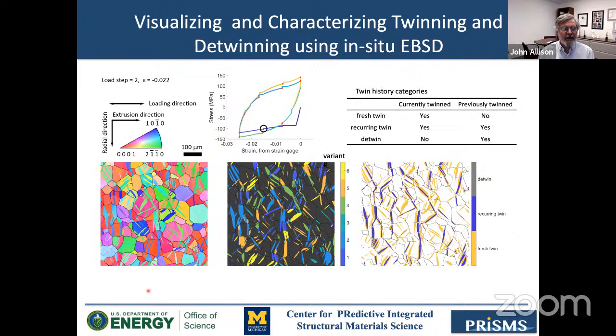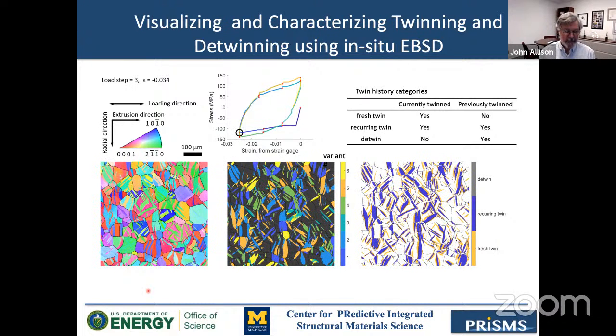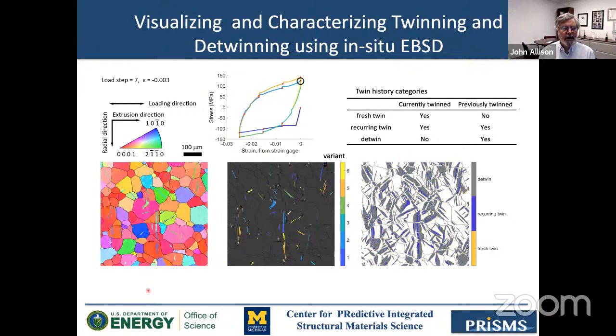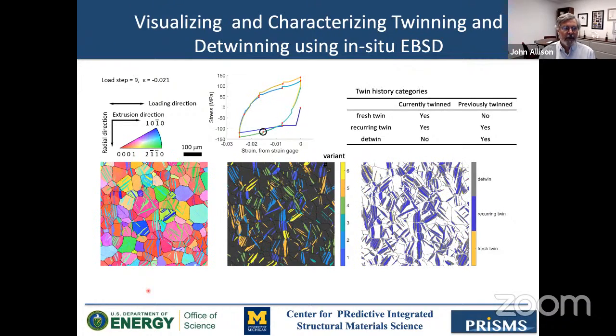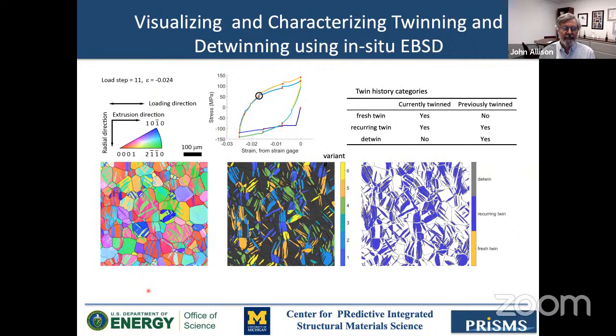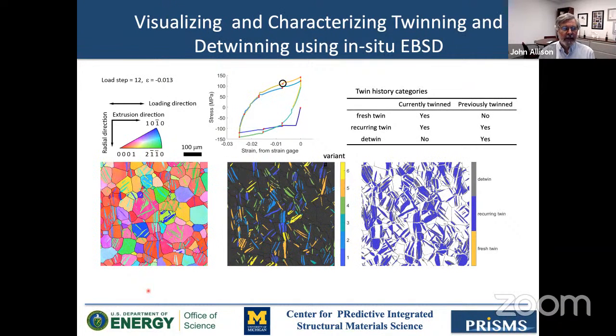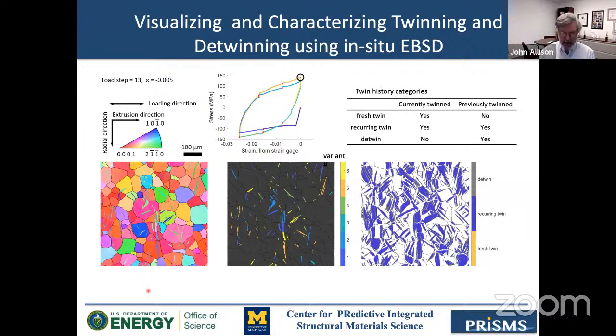But then we can continue to go under load. You see the twins grow, so they widen. That's the twin growth that's going on, and they get fatter. And then we unload, and they start to shrink, and on reload they start to appear in exactly the same place. And we can now determine these variants.